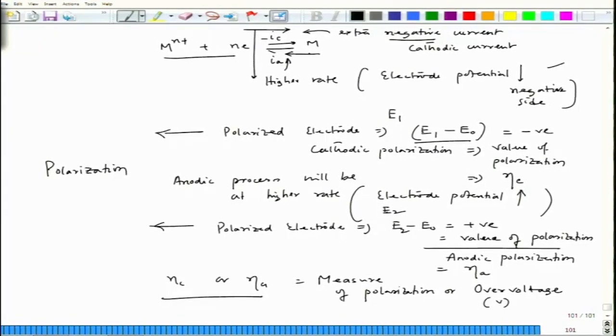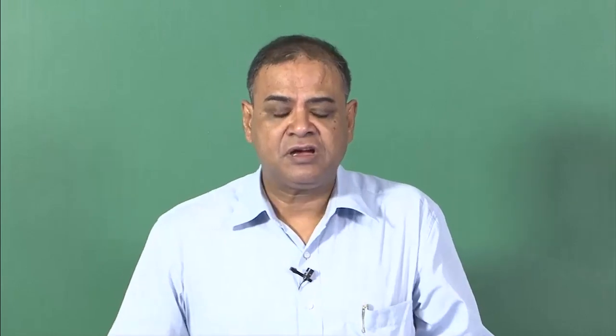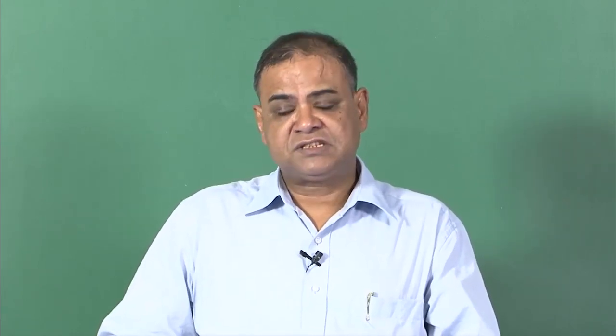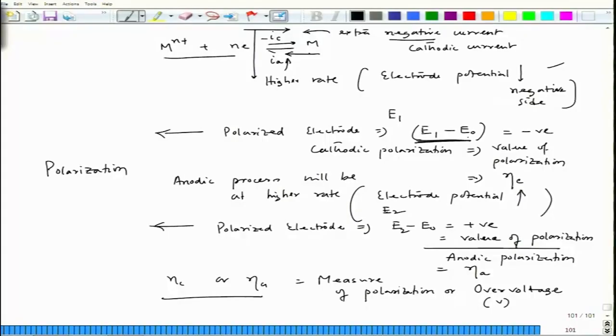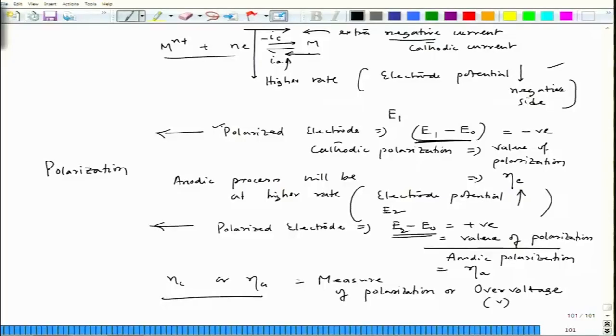So, from this particular discussion, what we see is that the polarization happens because of the supply of extra current, either on the positive side or negative side, or either extra cathodic current or extra anodic current. And if we send extra cathodic current, the potential drops from the equilibrium potential, which is E0 here. And when we send extra positive current, or we call it anodic current, then the potential increases from the equilibrium potential, which is E0 here also. And the difference in that potential, we call it the measure of polarization. In this case, it is cathodic over polarization. In this case, it is anodic polarization.